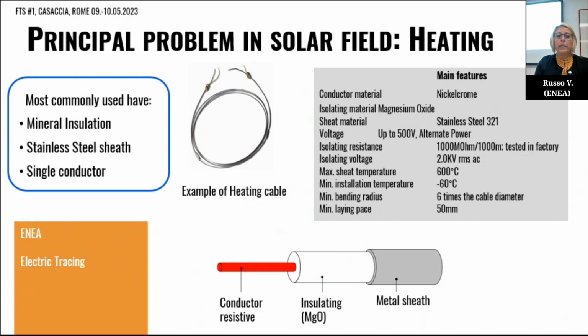Generally the cables have a mineral insulation, a stainless steel sheath, and a single conductor. Here in this table are summarized the main features of the cable used in a solar plant. Generally the conductor material is nickel chrome, the insulating material is magnesium oxide, and the maximum temperature allowed is 600 degrees, and so on. Here is the scheme of the cable, and it's possible to note the resistive conductor, the insulation, and the metal sheath.